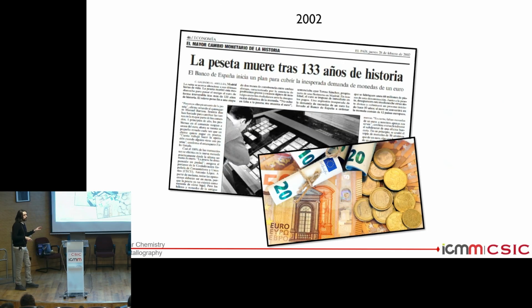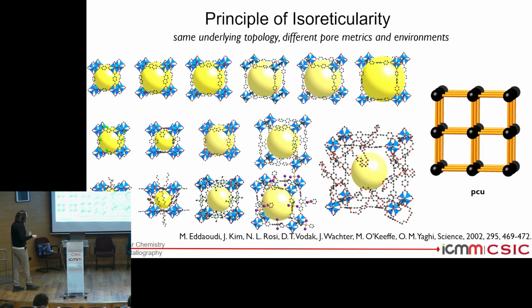2002, that's also an important year, not only for the MOF community, but, as we'll see, it was also important for MOFs here at ICMM. And in 2002, this paper came out. That was a very important paper where this principle of isoreticularity was indeed demonstrated with this family of compounds. All right, so here you can see, in this paper they reported how you can have all these series of compounds with the same secondary building unit, the same carboxylic, the same tetrahedral zinc oxo cluster, combined with a series of linkers with different lengths, different chemical functionalities, all of them giving the same topology, but with different pore sizes, surface areas, but also decorating the interior of the pores with different chemical functionalities, for example.